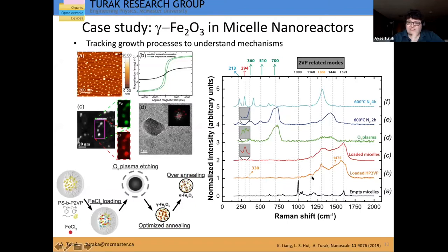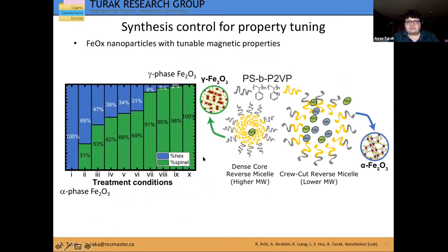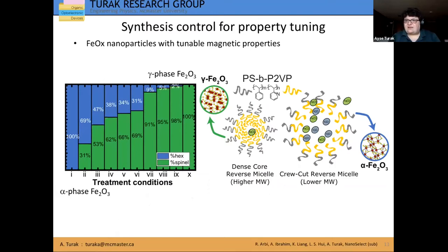That complexation leads to a very nice signature — peaks that exist when we see strong complexation between a salt and the vinyl pyridines — that allows us to track this process under different conditions. That kind of understanding of the mechanisms allowed us to produce tunable magnetic materials, going from purely antiferromagnetic materials as the alpha phase, all the way to the gamma phase where it was 100% gamma, just by tuning certain deposition parameters. Understanding that the micelle acts as a shielding environment, by tuning the amount of water that can infiltrate inside the micelle, and in addition to the precursor itself, we can tune this behavior across the spectrum to get designer materials to order.